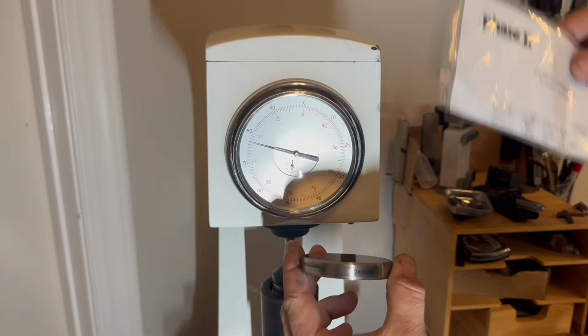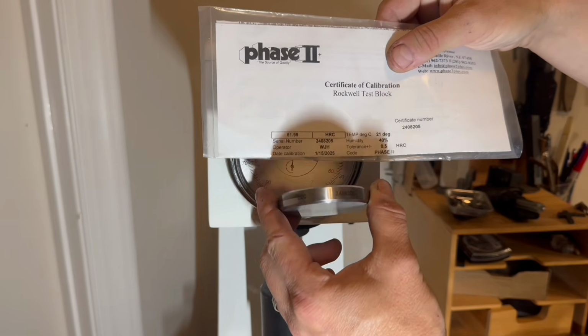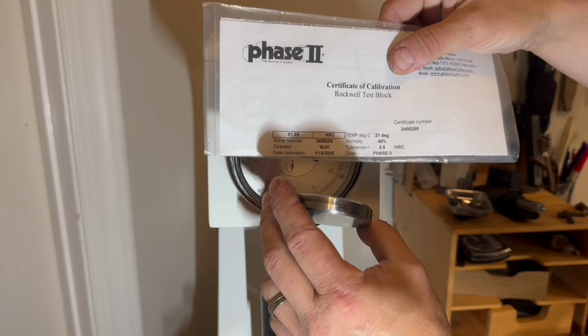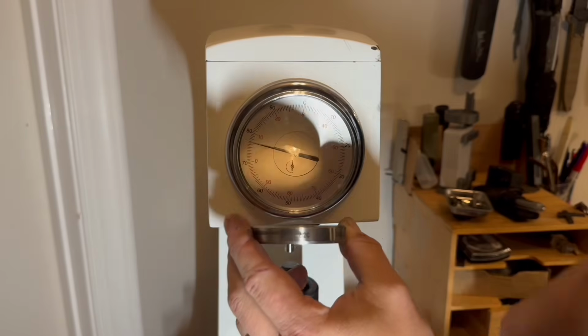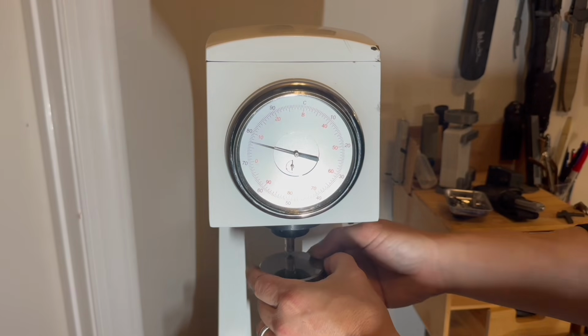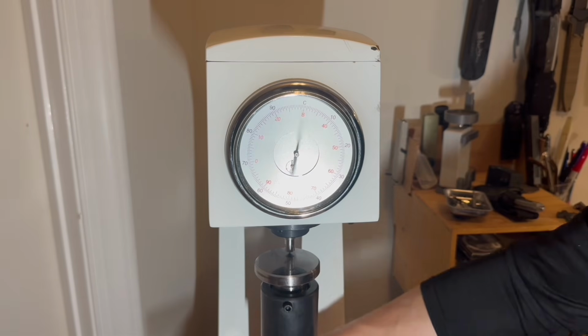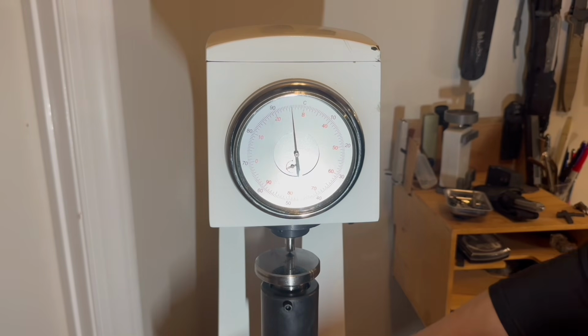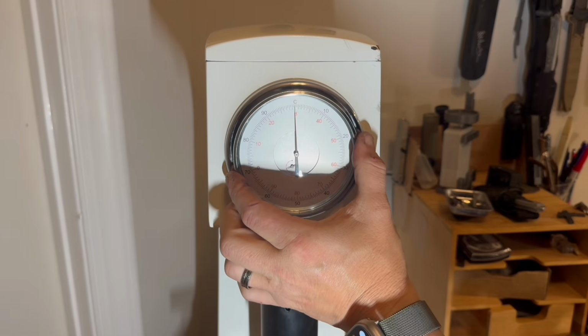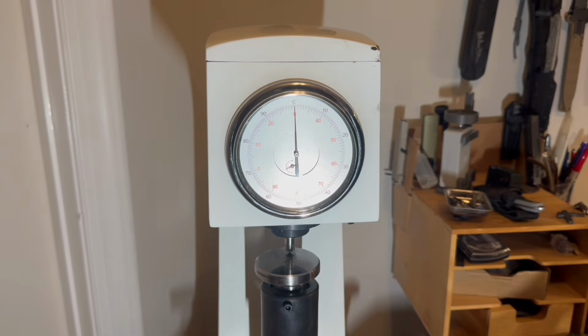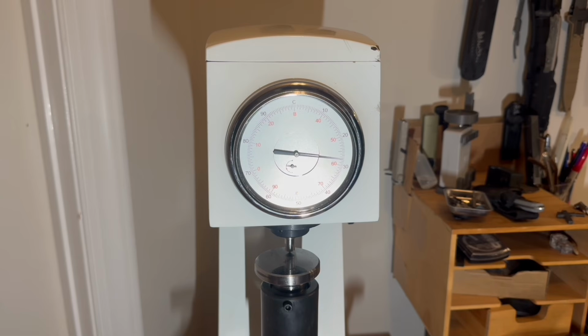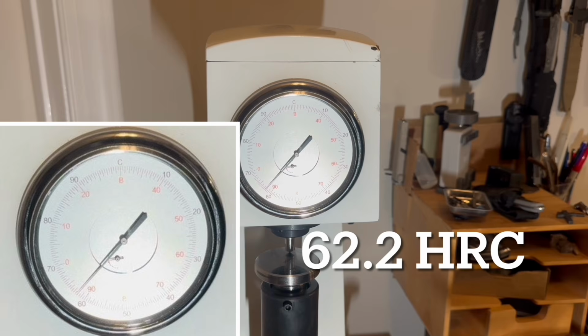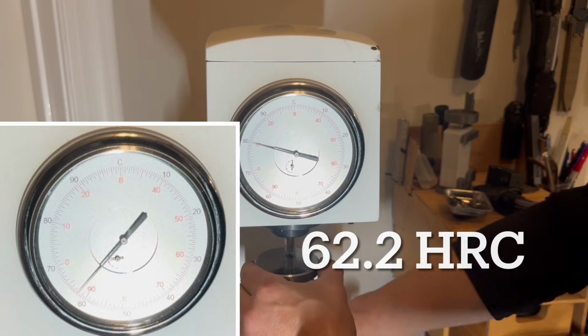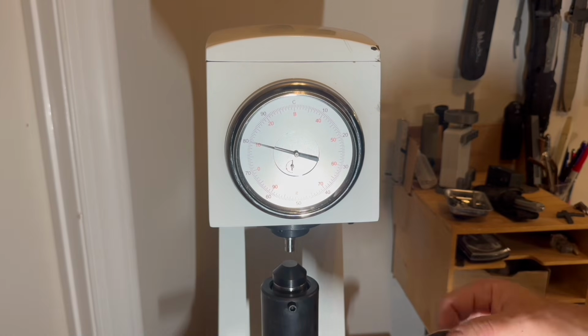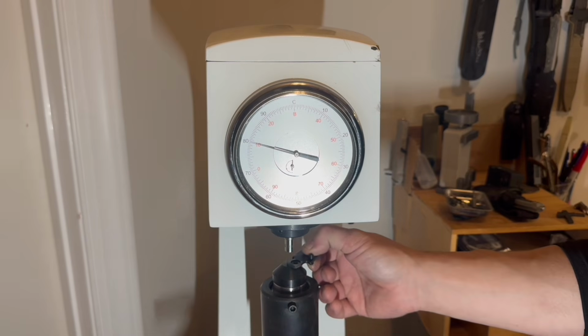Before I start hardness testing, I am going to show you that my calibration is still good. For that, I'm using my independently certified, serialized, and rated 62 HRC test block. I'm going to do a poke and see if my device is within repeatability calibration of plus or minus 1/2 of the HRC point. The video, by the way, is accelerated. Our first poke yields 62.2, which tells me I am within the calibration. And now I am testing the blade.